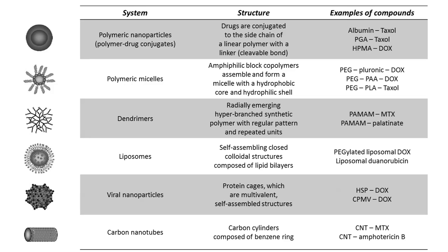Again, liposomes. We've mentioned liposomes. These are self-assembling closed colloidal structures composed of lipid bilayers. Lipid bilayers are used to construct cells in the body. These seem to be a great system for drug delivery. They are probably the most biocompatible architecture that we have. This is why a lot of the FDA approved nanoparticles for drug delivery are based on liposomes. These specifically can be surface functionalized with PEG, polymer PEG. That's been done in several studies. There are also viral nanoparticles, and to some extent, some carbon nanotubes are being used to encapsulate some drugs for cancer delivery therapies, drug delivery therapies, excuse me.